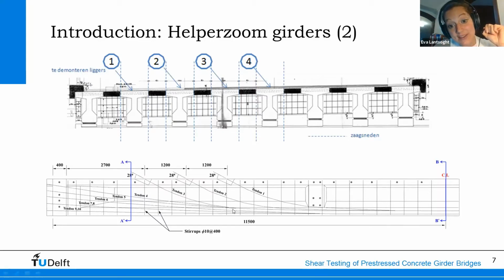And here you see the tendon profile. As I mentioned, this is a special detail, but tendons 1, 2, and 3 are anchored in the top flange. So that's quite a special tendon layout. And you see here all the other tendons and their position. You also see that there is very low stirrup reinforcement: a diameter of 10 millimeters at 400 millimeters on center.